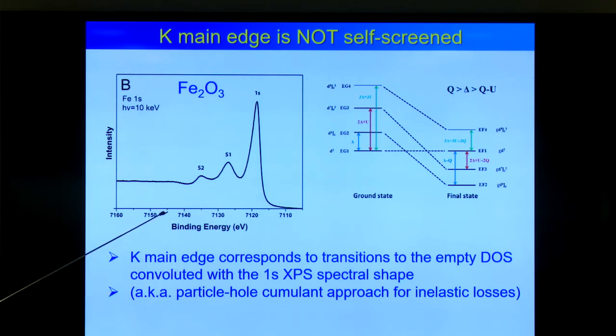So is this important? It is important for strongly correlated oxides, like iron oxide, and certainly for rare earths. If you go to high valency, almost everything becomes the main peak, and you have no satellites. If you do silver, gold, things like that, then there are no satellites, so then you can forget about it.